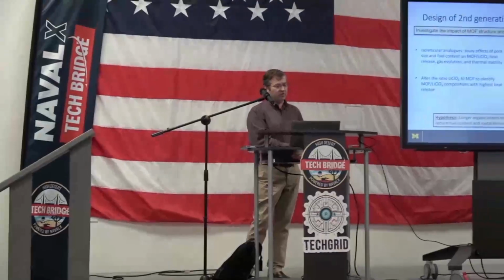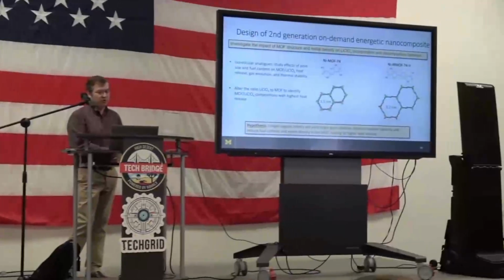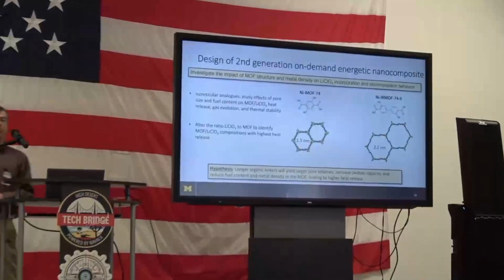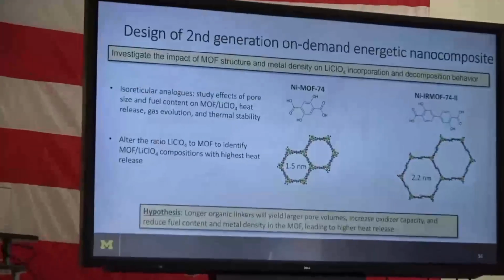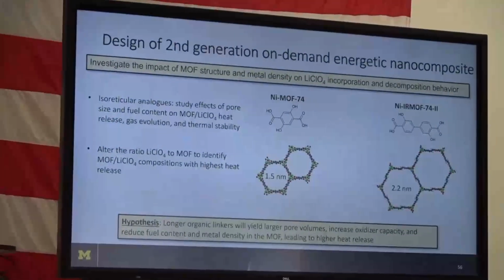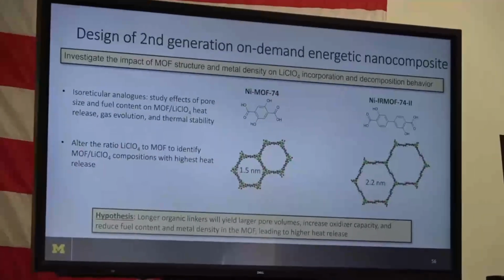We can also use that to control the pore size. By using a longer linker, we can make these pores, let's say, 2 nanometers, and that allows us to put more oxidizer in. So let's look at how that affects things like the oxygen balance. If we add 1.5 nanometer pores when we use this linker, we're up to 2.2 nanometer pores when we use this extended linker. And we can structure them both with our catalytic nickel